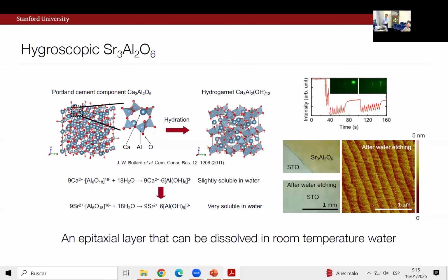So you may be surprised, how can you do some very simple soluble buffer layers using this system? But this is the key point. The aluminum oxide network does not extend in 3 dimensions, but it has this ring such that you can solvate both of these species.